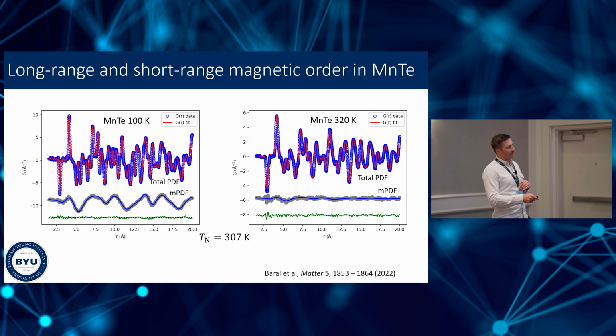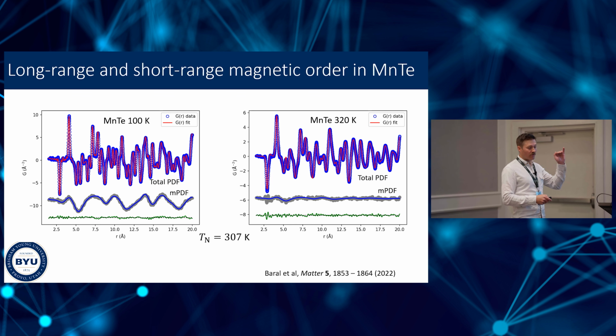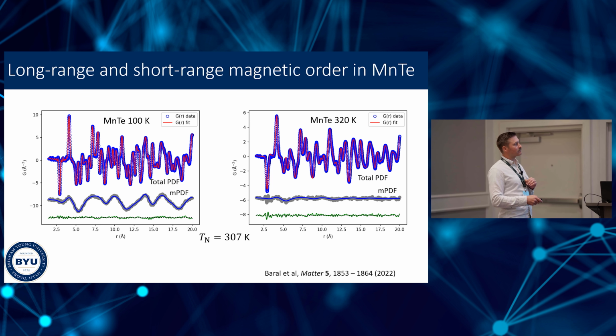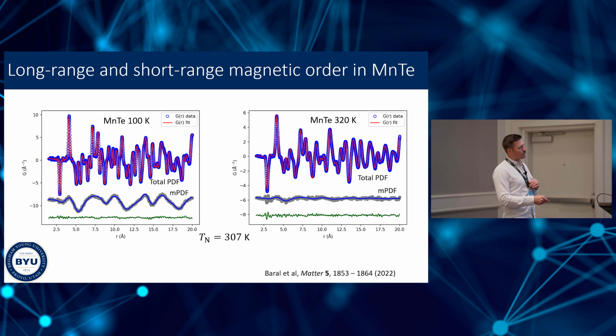At 320 Kelvin, which is above the ordering temperature of 307 Kelvin, we still have very clear wiggles in the magnetic PDF channel down here, but they die out after 15 angstroms or so. So this means we have short-range magnetic correlations, which we can very clearly see in our data, that are persisting into the paramagnetic state. All right.